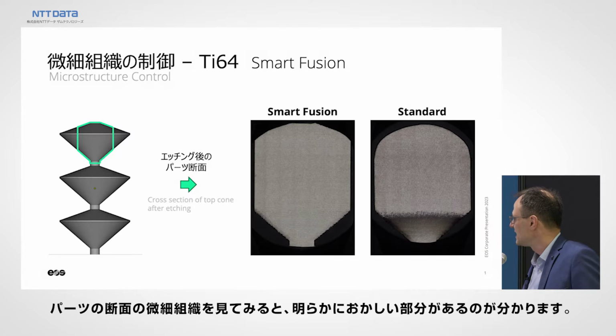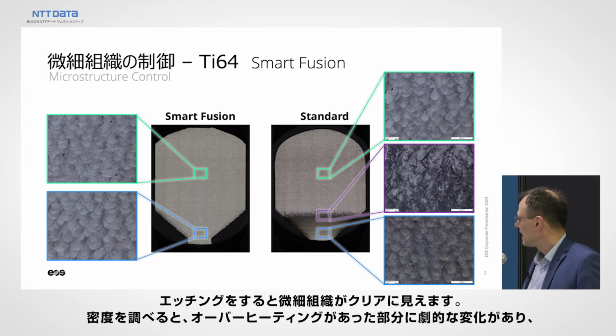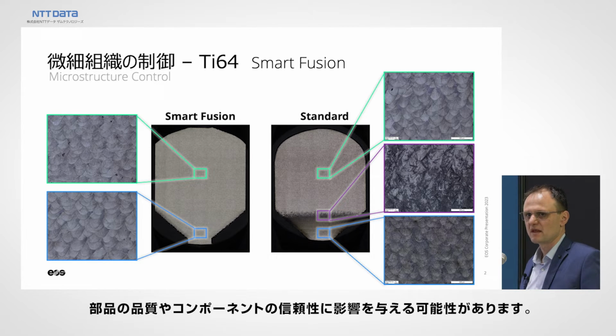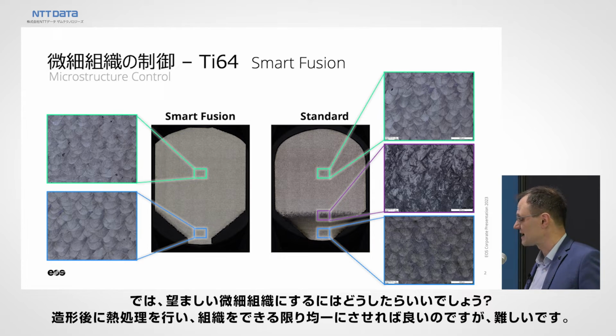Just not very nice. And if we now take the sample and cut it open, from the microstructure you can clearly see that there's something odd going on in here where this transition is happening. So that here does not look really normal. And if we start to etch the part, you can clearly see that the microstructure that you are very used to from, for instance, density cubes, in areas that have seen overheating is dramatically changing. And that can lead to problems in the qualification of your part, in the quality of your part, in the reliability of your components. So how are you going to take that as a starting microstructure, do a heat treatment afterwards to make it as uniform as possible?